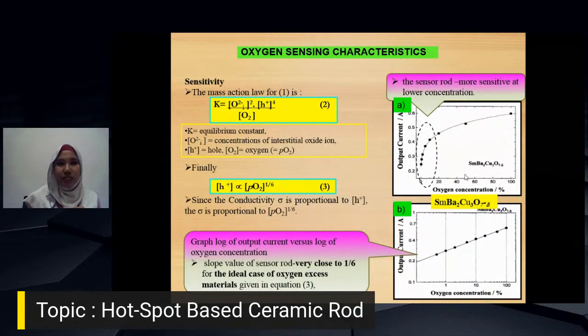Next, for the oxygen sensing characteristic, it's also about the sensitivity of the sensor rod. Here is the mass action law for equation 1, where K is the equilibrium constant. From this equation, the constant relates the interstitial oxide ion and the hole, divided by the concentration of oxygen. Finally, by rearranging that equation, we get the hole concentration proportional to the oxygen partial pressure to the power of 1/6. Since the conductivity is proportional to the hole concentration, this means the conductivity is proportional to the oxygen partial pressure.